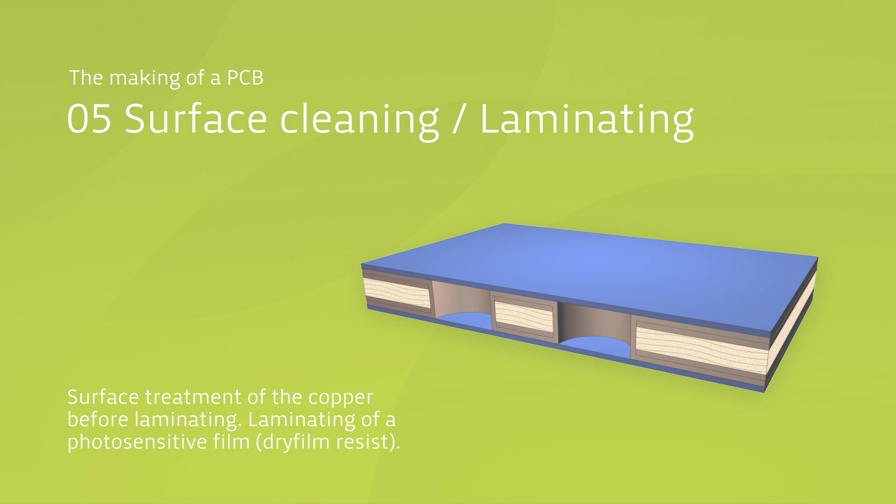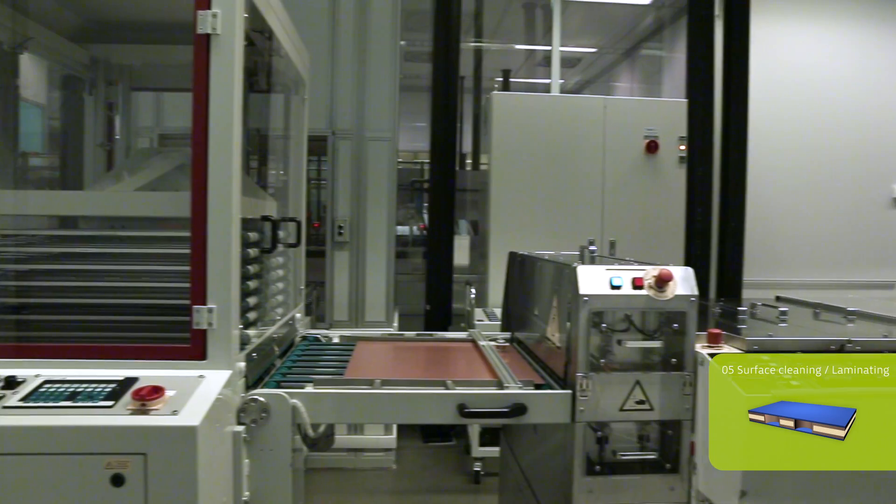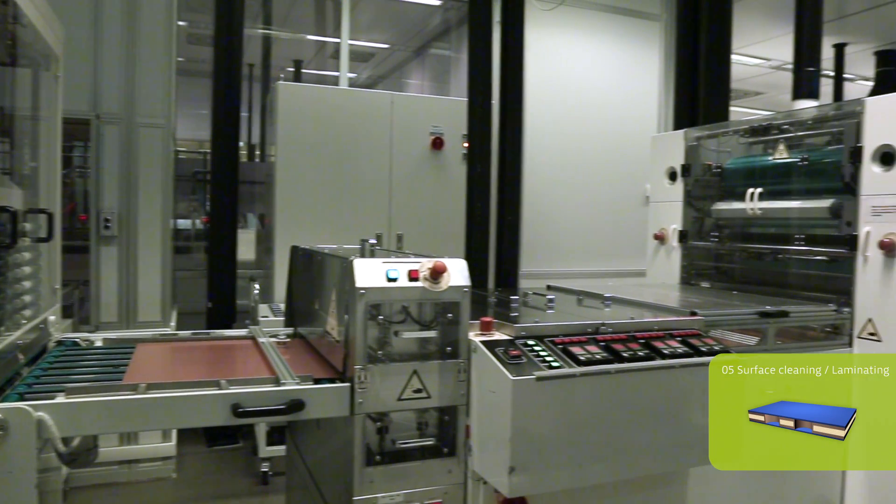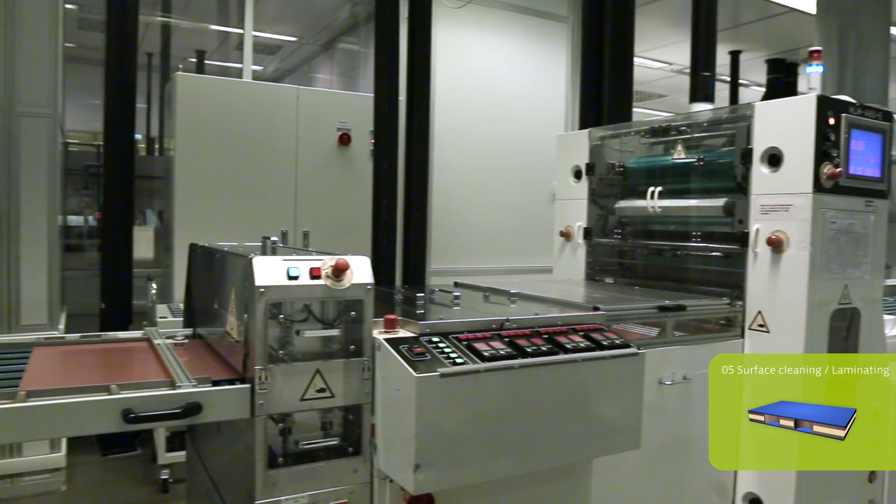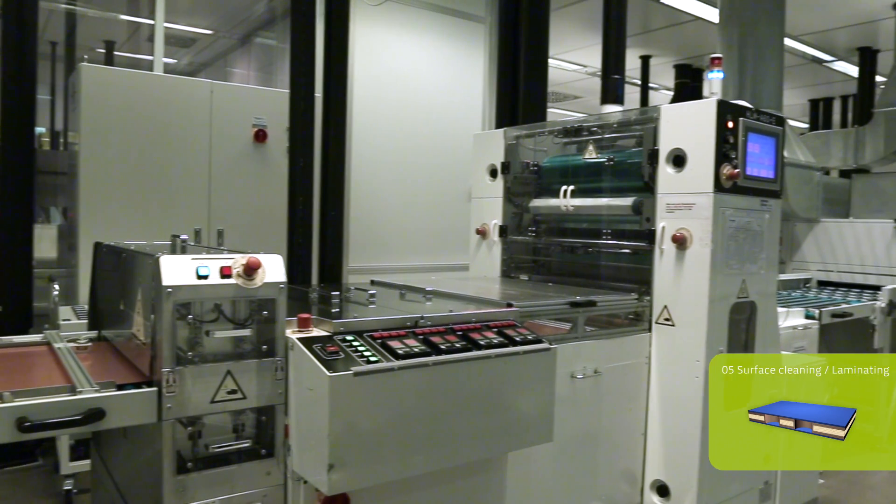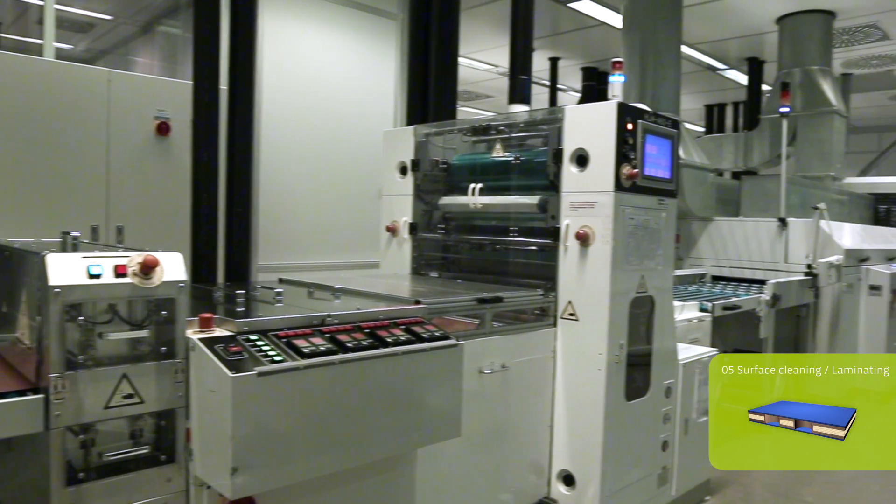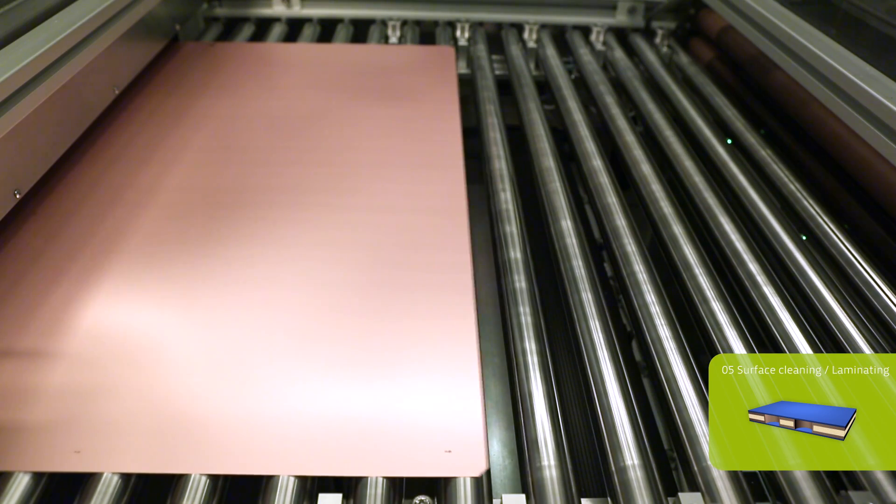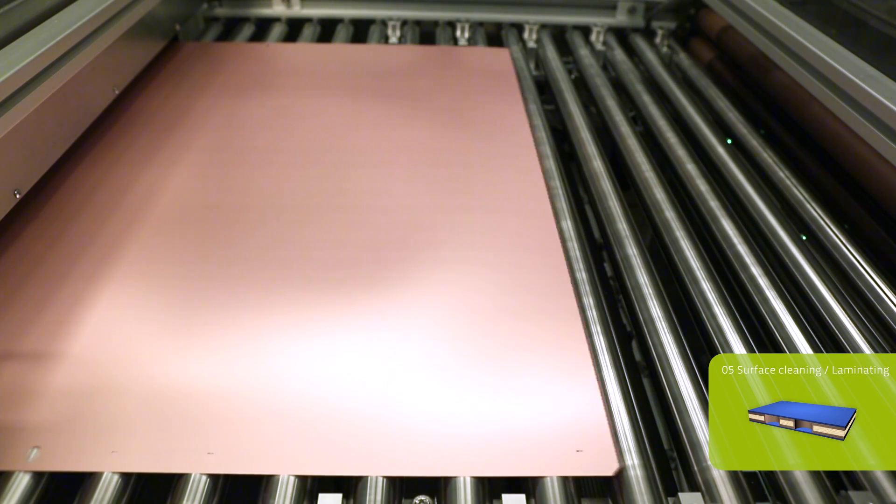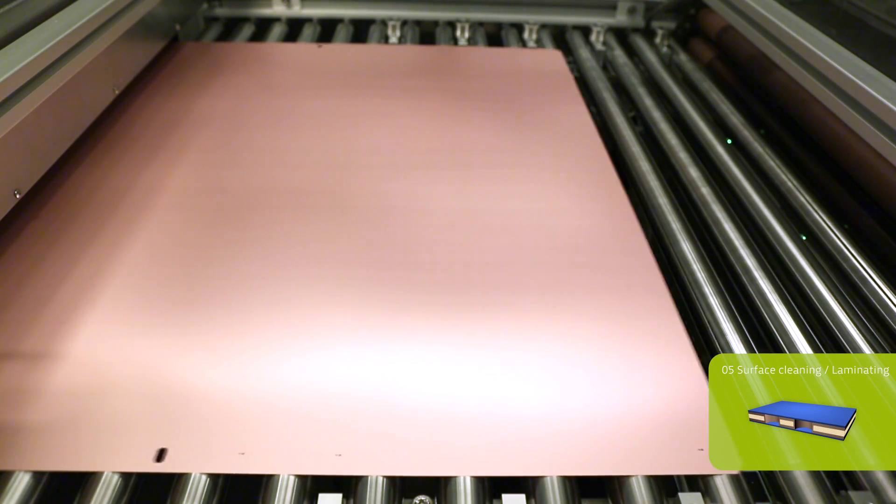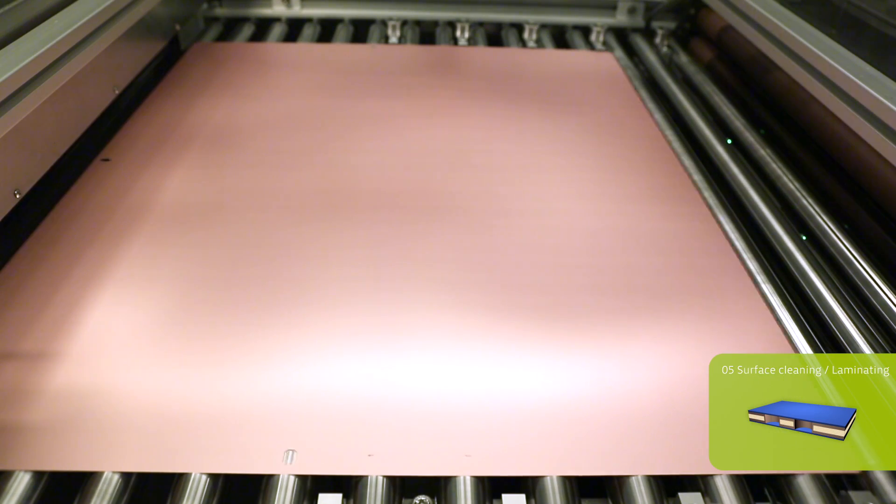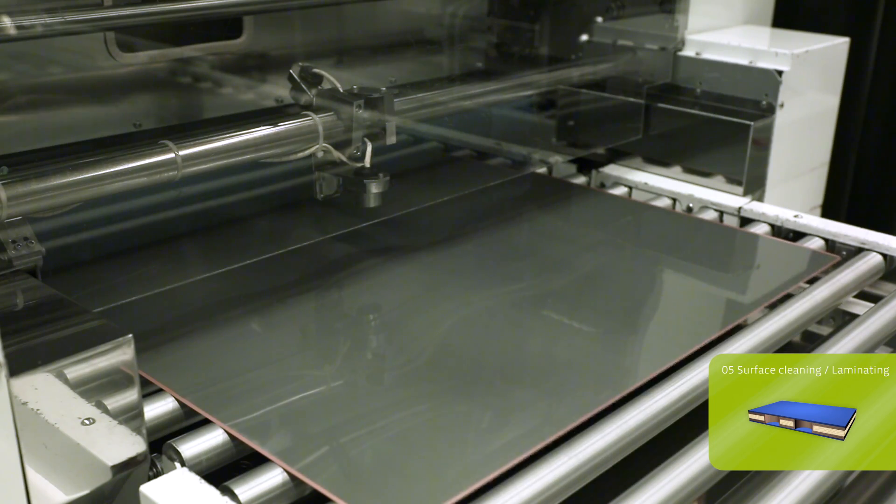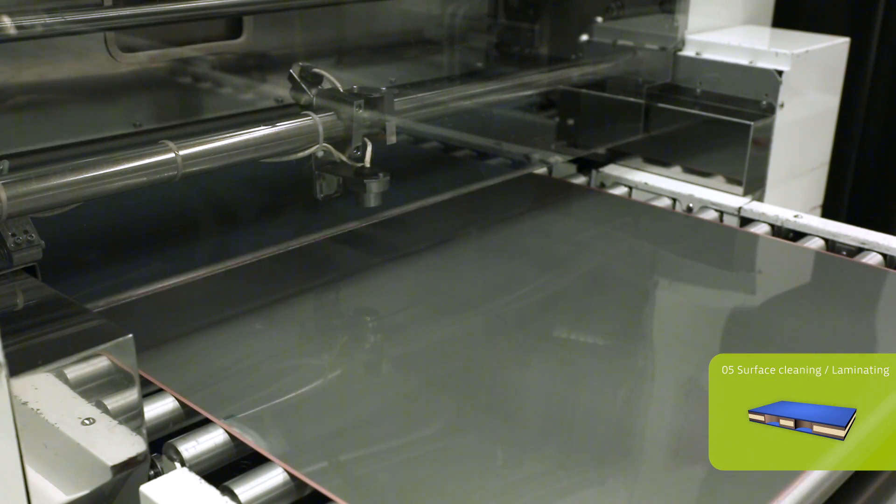After pre-cleaning, it enters the preheating zone of the laminator. The laminator is located in a clean room which is illuminated with yellow light to prevent the photoresist from exposure to UV light ahead of time. The rollers of the laminator apply the photoresist onto the entire surface of each side of the panel.